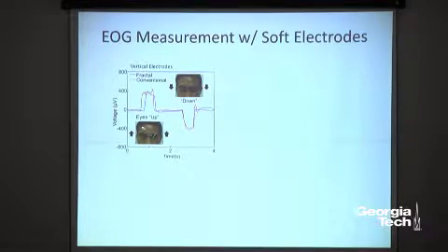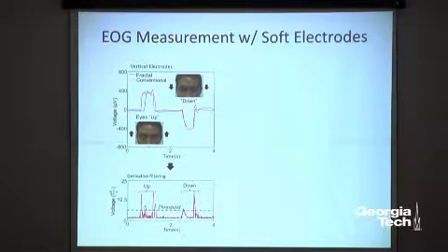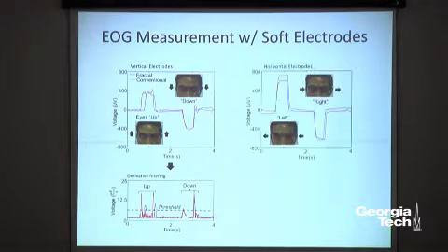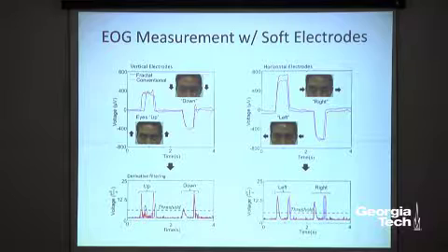So now you see this guy is moving his eyes up, down. You have about 400 microvolts of biopotential. And you can filter them to have this nice peak based on threshold. At the same time, you can do horizontal motion recording, right? Left and right. Okay? And here we have two different curves. The blue one is the mesh pattern fractal soft electrode, and the red one is the conventional gel-based metal electrode. We have a simultaneous comparison. Looks pretty similar. Right?